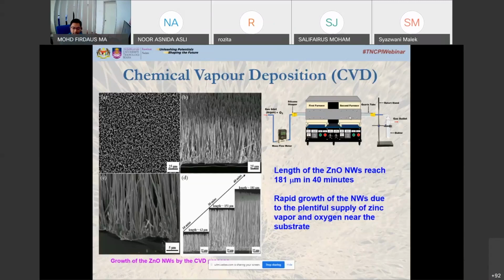So the silicon substrate is here. The reactor pressure was kept at a certain level, usually 4 to 5 torr, and the oxygen-argon mixture is allowed to flow inside the reactor at a constant rate. The temperature is set during what we call the optimization process, and it is usually more than 400 degrees Celsius. The deposition time in this case was varied between 10 to 40 minutes. You can see here that the length of the nanowires increased from 63 micrometers to 181 micrometers.